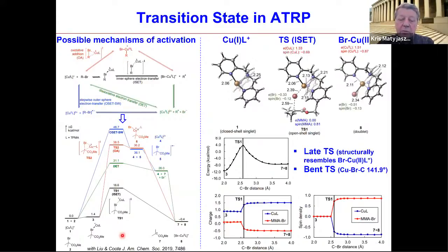We calculated, together with Michael Coote and Peng Liu, transition states for these three reactions. You can see that the lowest transition state energy is for the inner sphere electron transfer process. The dissociative electron transfer has 14 kilocalories per mole higher activation energy. This corresponds to a reaction rate approximately 10 to the power 14 times slower. So if this reaction had a half-life of 1 second, this one would have 3,000 years. And this one would have maybe not 1, but 15 billion years, essentially from the time of the Big Bang, because the activation energy is now 30 kilocalories per mole higher. So how does the reaction occur?